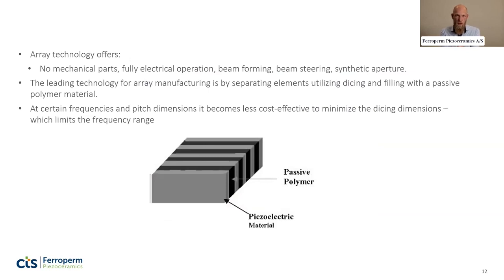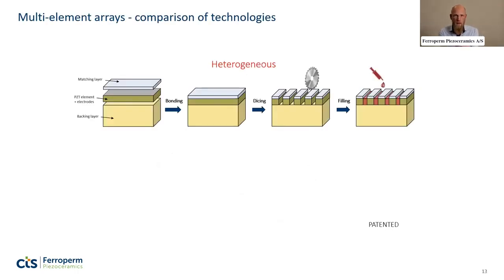So this was about a single element transducer using thick film, and of course the next application you would have in mind is, why not make arrays? So this is something that we worked on as well. If we think about the conventional way that arrays are made for high and low frequency, is that you have some kind of assembly process with the discrete components. There's a backing layer, there is a PZT element, and then electrodes, obviously, and then a matching layer. So this has to be individually manufactured and then assembled somehow through a bonding process. Then you can dice it up to make your composite usually, or to make discrete array elements.